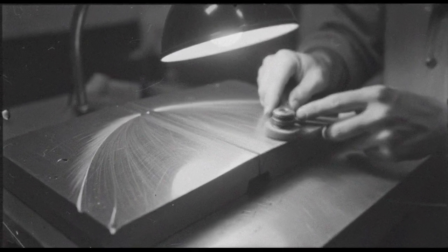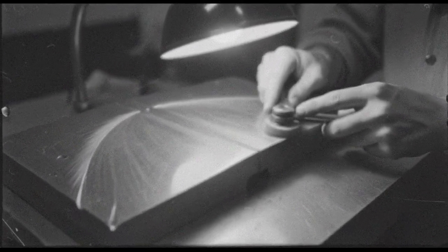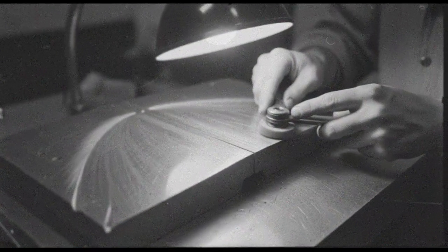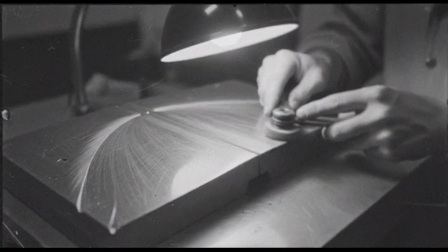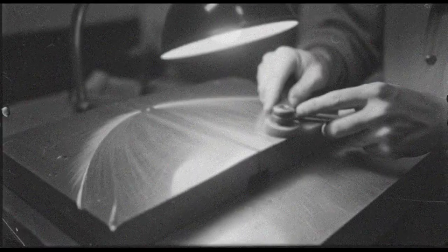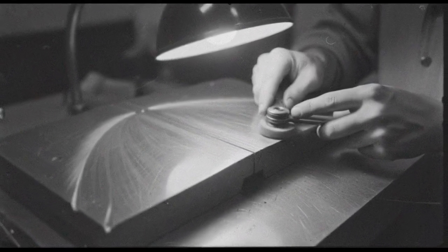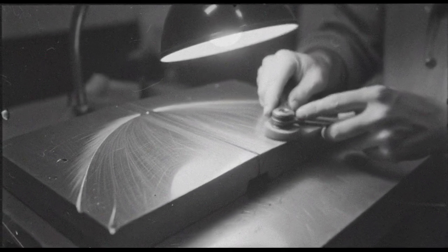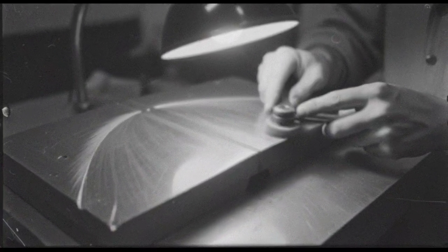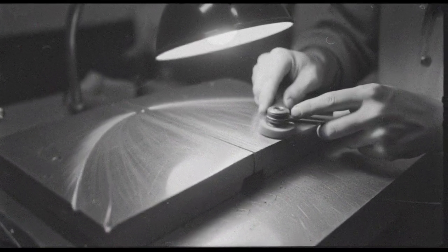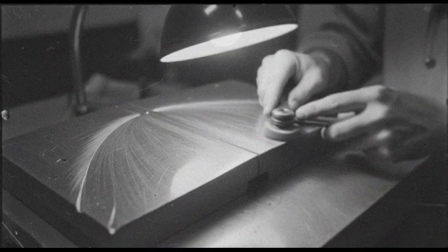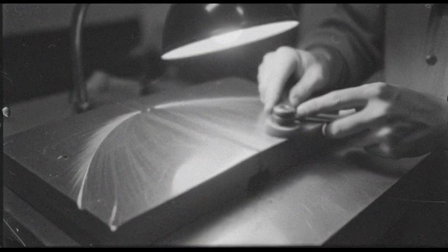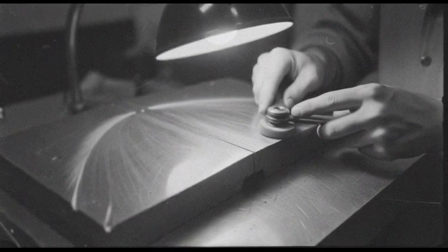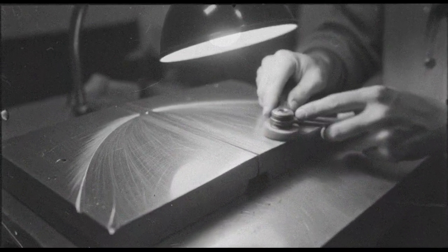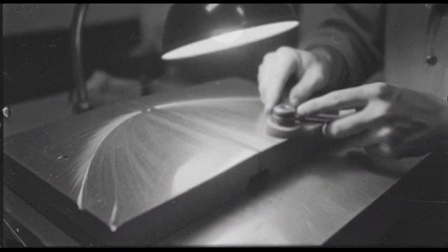The first clue came during the hardness tests. The new samples were softer. Not dramatically so, but measurably, significantly softer than the Kursk Panthers. Makonin ran the tests again, thinking perhaps there was an error. But the results were consistent. These armor plates had lower hardness values across the board. That was strange. Why would the Germans be producing inferior armor for their best tank?